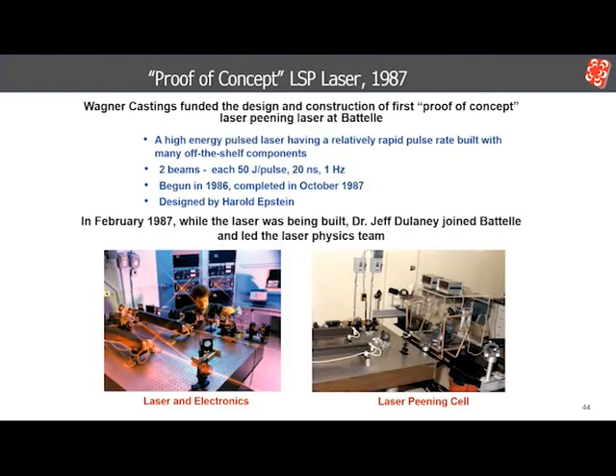For Wagner to demonstrate the commercial feasibility of laser peening, they would need a laser with a small footprint and a pulse rate much greater than 1 every 8 minutes. By 1986, Wagner made the decision to fund the design and construction of a small footprint laser providing 2 beams of 50 joules each, 20 nanoseconds, with a 1 Hz pulse rate. The laser was designed by Harold Epstein and built at Battelle.